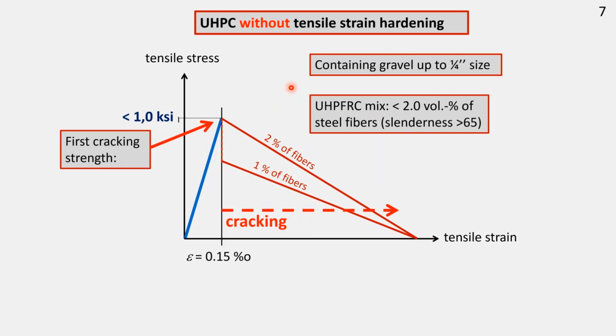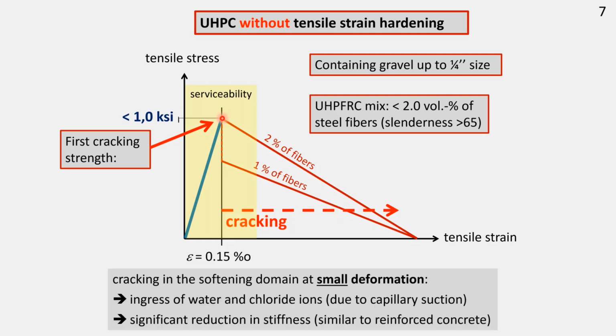Now, when we have lower fiber content, and I intentionally call this material UHPC, it usually has no tensile strain hardening. What happens? We have an elastic domain. We come to what is usually called the first cracking strength, and then we have the descending softening branch. Or if the fiber content is very low, we have a drop and softening. And cracking occurs already when we arrive at the first cracking strength. So this means we are in the middle of the serviceability domain when cracking occurs. So cracking in the softening domain at small deformation, and we need to count on ingress of water and chloride ions in this domain, and a significant reduction in stiffness when it comes to structural performance. That's why I'm insisting on UHPC or UHPFRC with tensile strain hardening.